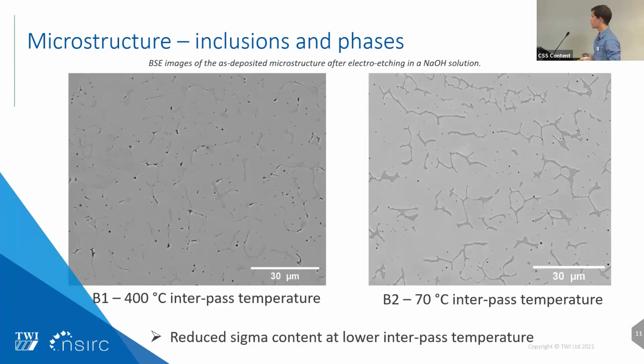At the beginning, I mentioned that I had two different walls, one with a higher interpass temperature of 400 degrees and the second one at 70 degrees and below. That was done after we realized that we had sigma phase within the original build. So we were trying to minimize the amount of sigma in the build by lowering the interpass temperature. The goal was, by lowering the interpass temperature, to have a higher cooling rate because the temperature of the substrate would be lower, and thus we would spend less time for a given point within the build in the sigma forming temperature range, minimizing the amount of sigma.